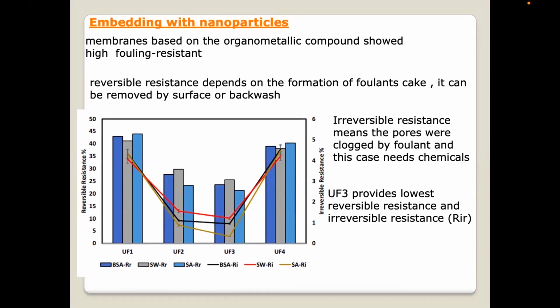Embedding with nanoparticles: a membrane based on an organometallic compound showed high fouling resistance. Reversible resistance depends on the formation of flocculant or foulant cake, which can be removed by surface wash or backwash. Irreversible resistance means the pores were clogged by foulant, and this case needs chemical cleaning. In this figure, UF3 provides the lowest reversible resistance and irreversible resistance, Rir.